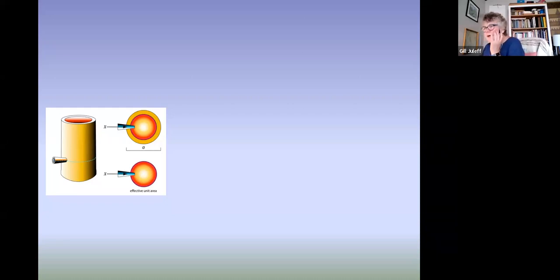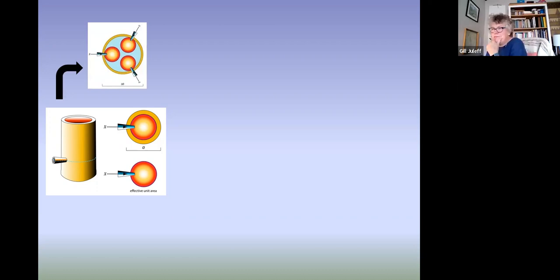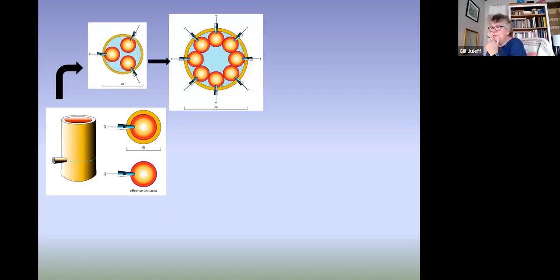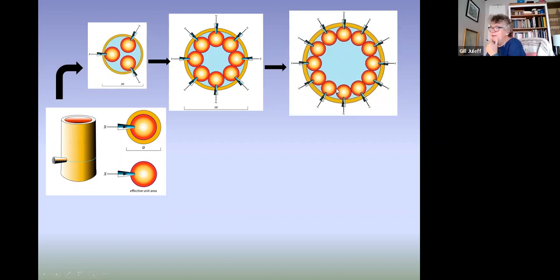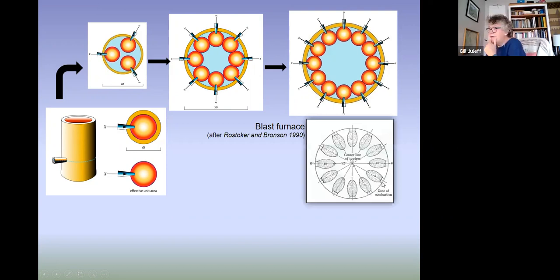So let's follow that idea through a little further, and I'm sure the engineers amongst you are going to come back and query some of this, but it makes sense to me. So you want to scale up and develop your shaft furnace. What you do is you add in additional effective unit areas. You have more points of airflow into your furnace, but as you scale up, you start to create this dead area in the center of the furnace. So just by increasing by 3 diameters, or greater, you start to put your furnace into a very difficult situation, because you now have a zone of combustion around an inactive column of fuel. And this is exactly what happened with the blast furnace. You have a real problem with this geometry.